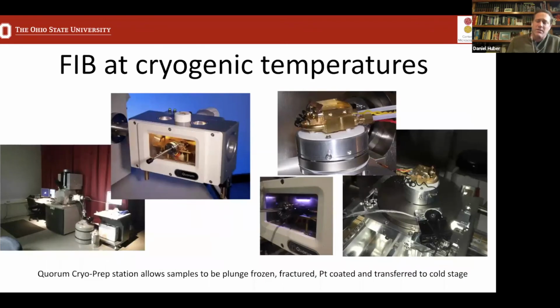We can also perform a lot of experiments at cryogenic temperature. So we have a Quorum cryo stage. Cryo stages are fairly common on scanning electron microscopes. They're less common on FIBs, but we're lucky to have one on our Helios. And the principle of doing the FIB work is pretty much the same. The process is that we will take a sample, put that into liquid nitrogen, and then transfer that onto the stage, and then onto the cryo stage, which is being cooled by cryogenic gas, which allows us to work on the sample in a frozen and hydrated condition.